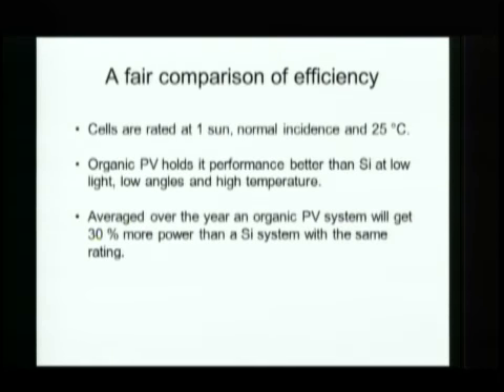One other thing I need to point out, when we talk about efficiency, we measure that under normal one-sun conditions at a 90-degree angle at 25 degrees Celsius, which is room temperature. But in the real world, early in the day, you don't have that much sunlight. The light doesn't come in at that angle. And in the middle of the day, the cells heat up. And it turns out silicon cells don't work as well at lower lighting levels, and when they heat up, their efficiency goes down. But organic solars hold their performance at lower light, and they hold their efficiency at elevated temperatures.